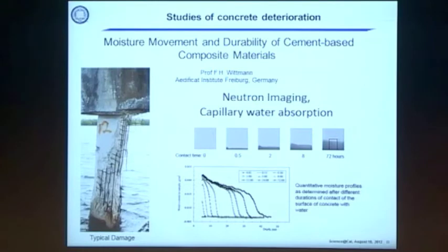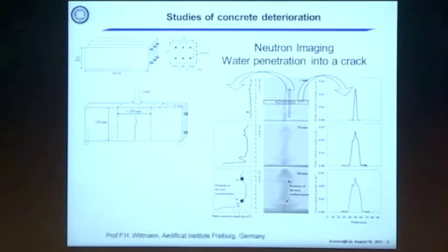But again, how can you study this non-destructively? Neutrons may be very helpful here. You can look at how water propagates for different concrete mixtures. These five images shown here demonstrate how water has been sucked by capillary forces into concrete. You can see where the front of water is, and you quantitatively measure how much water is in your concrete and how long it takes to propagate and so on. And you can look at salt in concrete.